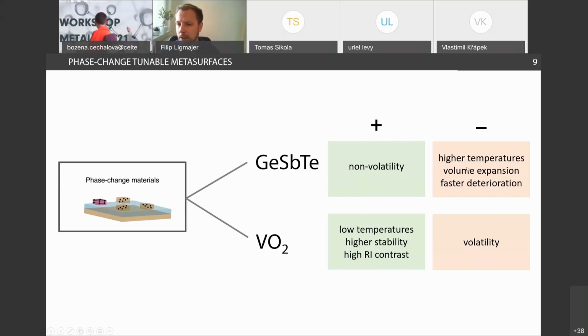It requires quite high temperatures for switching. It suffers from non-negligible volume expansion, and it deteriorates faster compared to VO2, which can be tuned or switched around 68 degrees Celsius, so quite close to room temperature. It has higher stability and also higher refractive index contrast, so it basically switches more in the optical or infrared range.